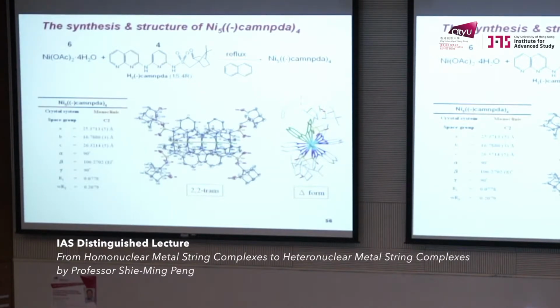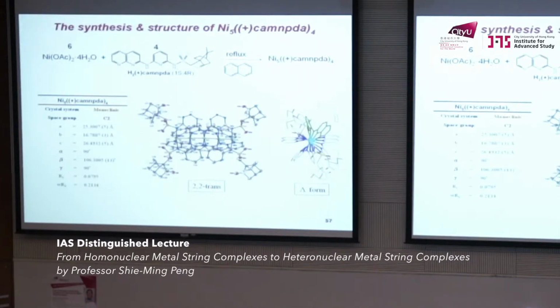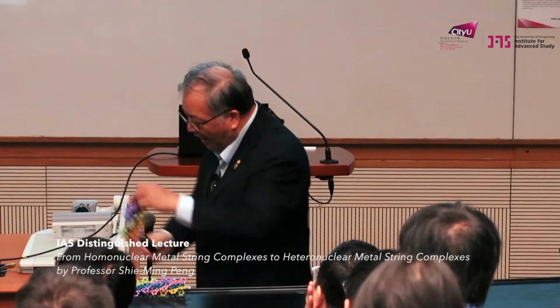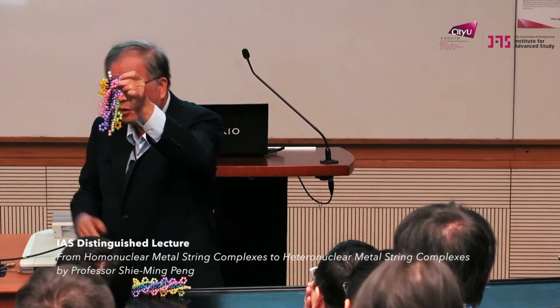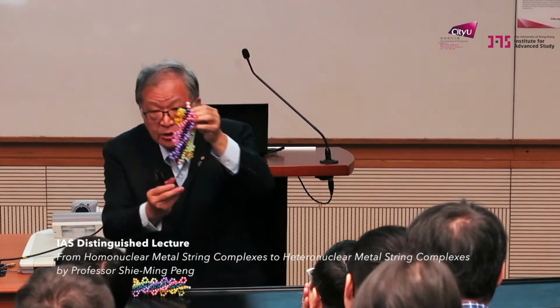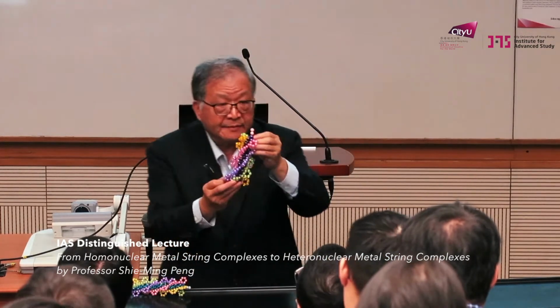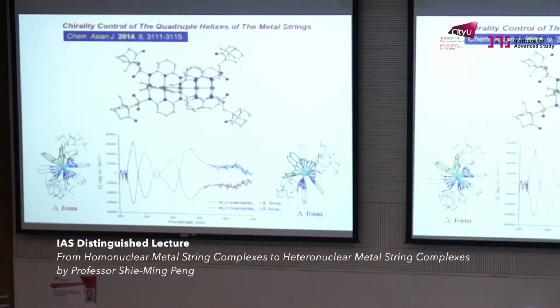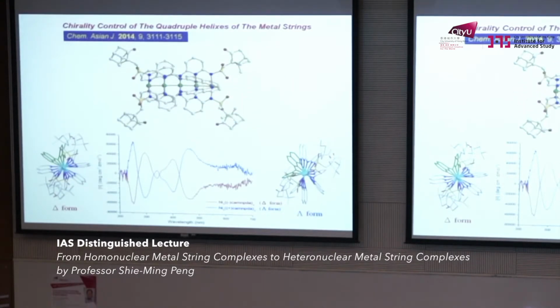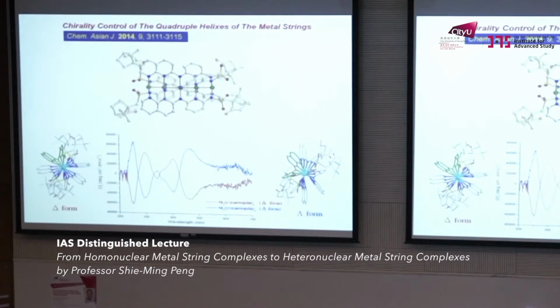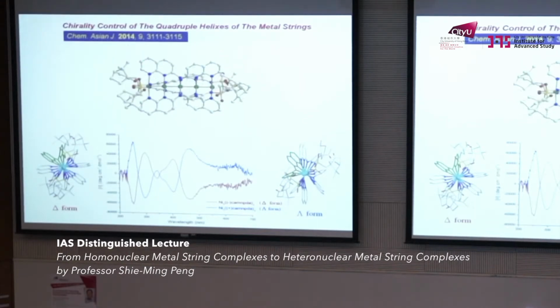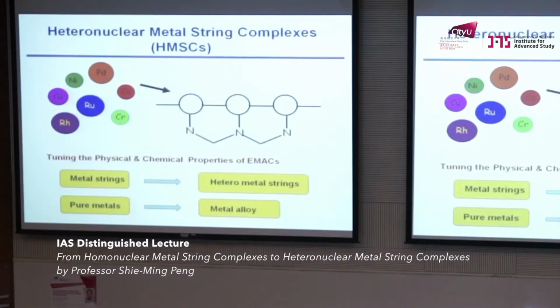We attach this ligand to one camphor, to make the chiral complex. With camphor minus, we can get the delta form, with camphor plus, we can get the lambda form. That means you use the chirality of the camphor to control the chirality of the quadruple helix. So we can get a bottle of left-handed or right-handed quadruple helix. And these two forms, even heated to 100 degrees for a few days, the CD spectrum remains, so they are not racemizing.